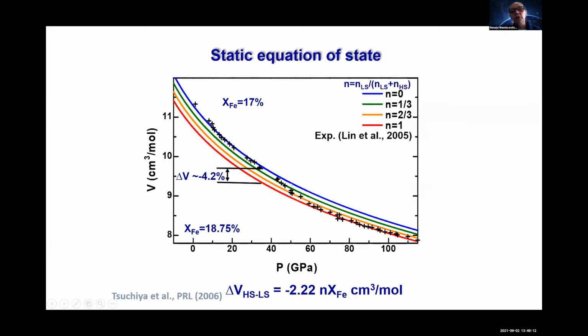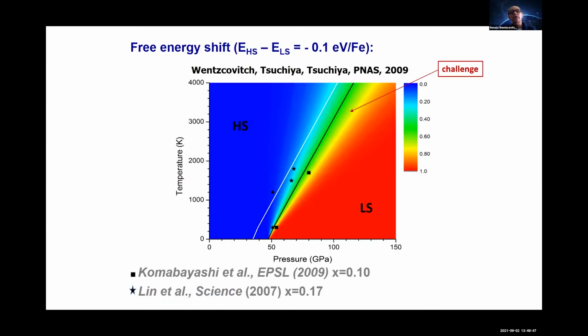But here, the blue is the compression curve in the high spin state in ferropericlase with 18.75% iron, and red is low spin. And when we compare to the experimental data, what we see really is a region in which the data crosses from the high spin prediction to the low spin prediction, and this is certainly a region where both spin states are present. This is the mixed spin region. The compressibility increases in this region, and the bulk modulus decreases in this region. This region of mixed spin state broadens and shifts to higher pressure with increasing temperature.